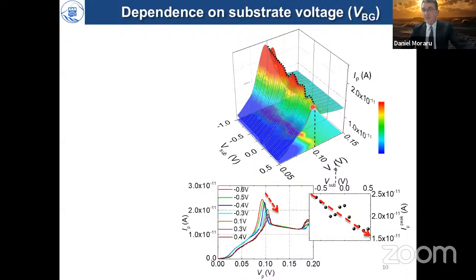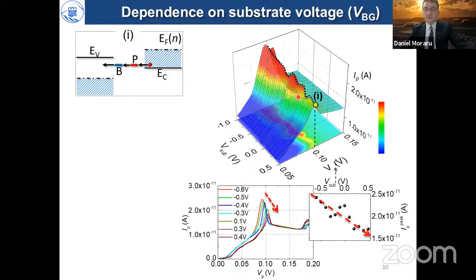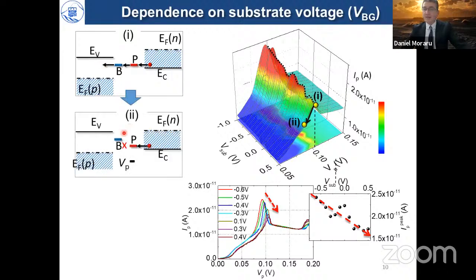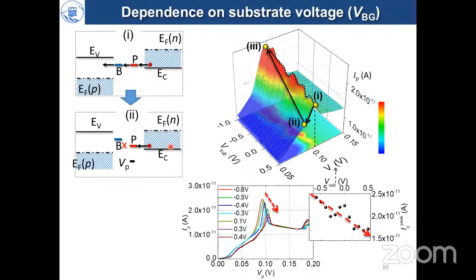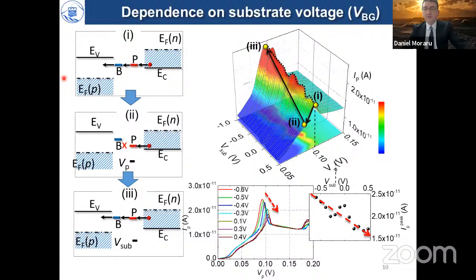So we start by interpreting this enhanced peak at point 1 by the alignment of a phosphorus donor on the right and a boron acceptor level on the left. And this allows us to observe this enhancement. But then if you apply, let's say, a more negative VP, then misalignment between these two levels could be obtained because of different coupling of P and B to the VP voltage. However, again, because of different coupling of these two dopant states to the backgate this time, we can achieve, by moving to point 3, a realignment of the two energy levels in the transport window, and thus we can move back on the peak and we observe the enhancement again.